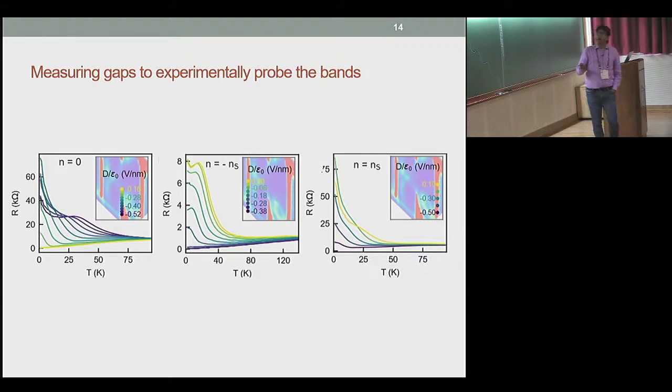Now, the position of this Moire gap, the density at which it occurs, tells you what the twist angle is. If you have many, many pairs of electrodes, we do see variation in that angle in the same device. This is well established. It's not really news. We're just confirming what people in the community see all the time. In these systems, no. The short answer is no.